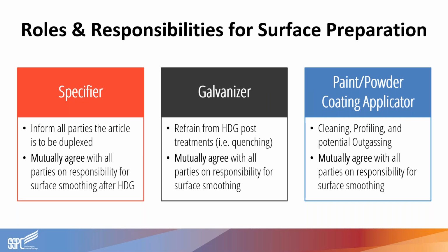Once all parties know that the material is going to be painted or powder coated, the galvanizer will be responsible for avoiding any galvanizing post-treatments that are commonly applied to help preserve the galvanizing appearance from staining, or to help cool the parts for handling. But there are certain conditions that are known to impact the adhesion of any applied coating afterwards. For example, when parts come out of the galvanizing kettle, they're very hot and can't be handled right away. So often they're rapidly cooled by water quenching or chromate quenching solution. These processes have been known to negatively affect adhesion of the coatings that are applied afterwards.